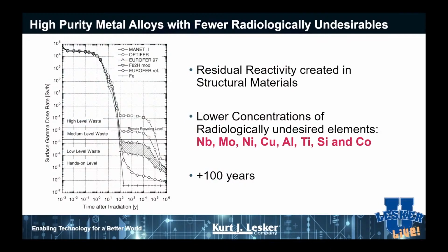Again, in terms of steels, here are a couple of popular steels that have been out there. The Europeans have been kind of leading the way. Eurofer 97 is a steel alloy that I'll talk about a little bit. To make it less susceptible to neutrons, they've tried to remove some of the elements in steel that are magnets for neutrons, with the idea that with all the side reactions that occur in the fusion reactor, the thing's cool enough that you can actually handle it within a lifetime or so.